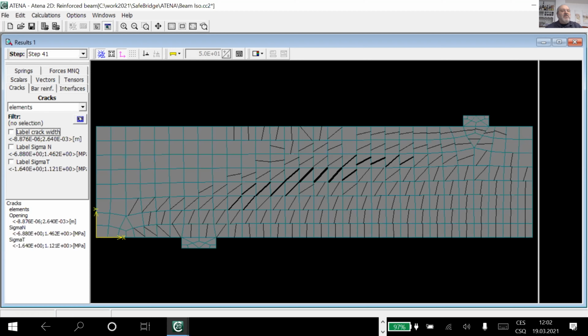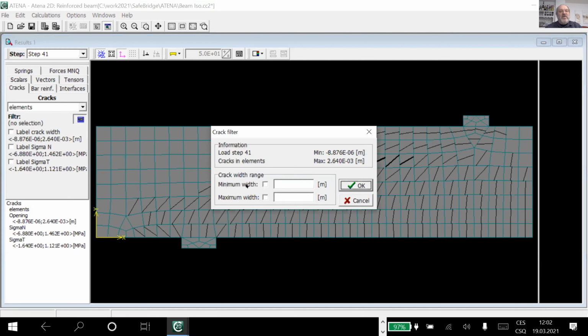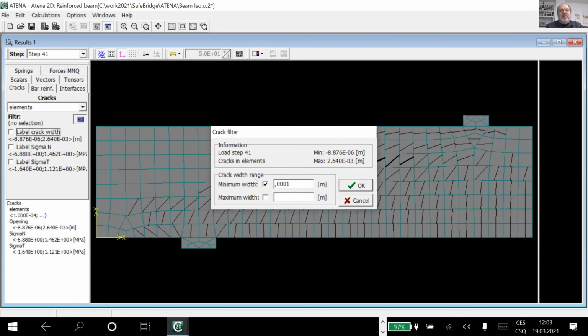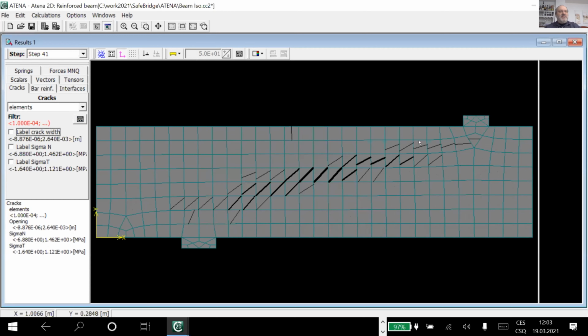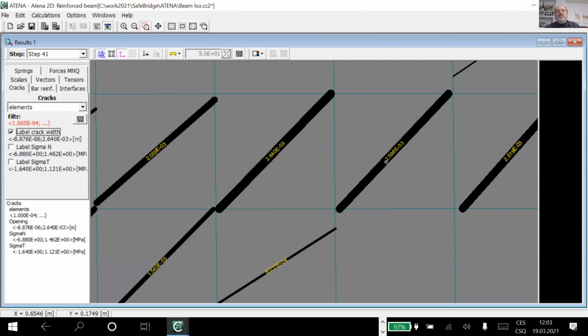And you can also make the filtering. So the maximum crack is, in this case, we are on the descending branch, 2.6 millimeter. So we can make the filtering, for example, again for 1/10 of a millimeter. So all these are over 1/10 of a millimeter. And if we label them, we will see, we have to enlarge it a little bit, then here in the middle, we have these cracks, which are about 2.6 millimeter.